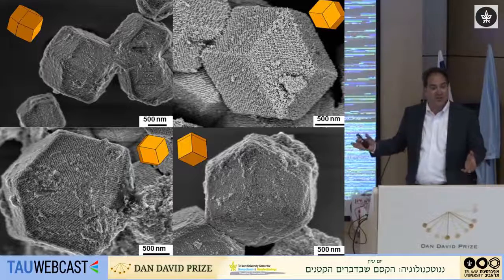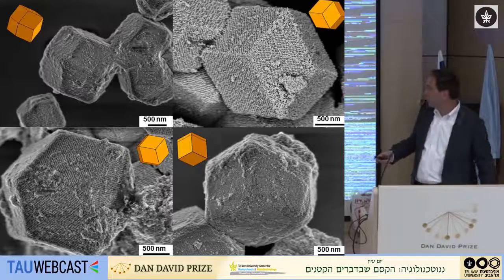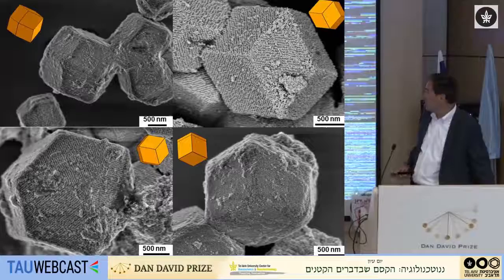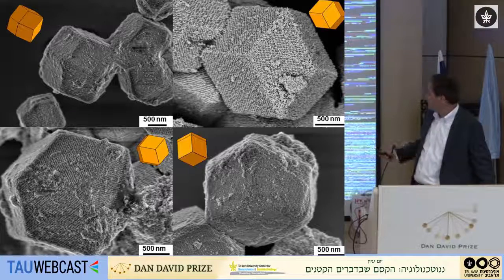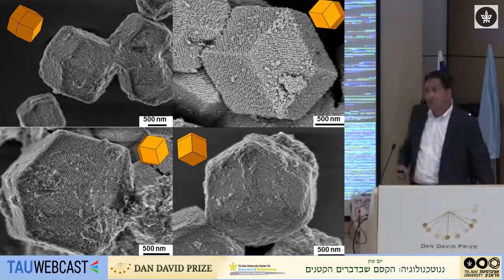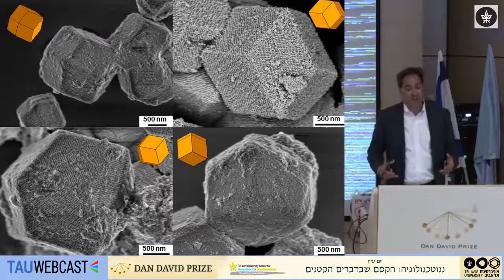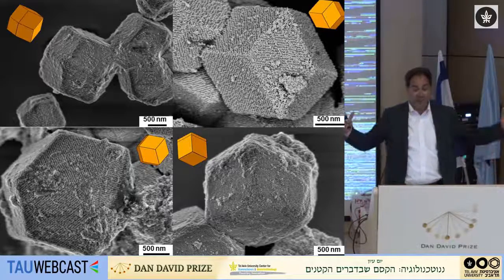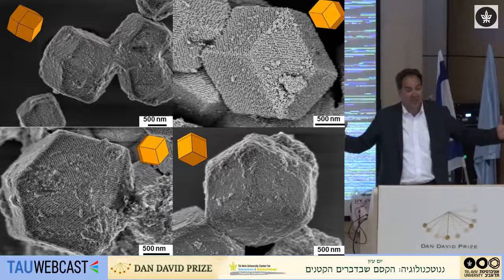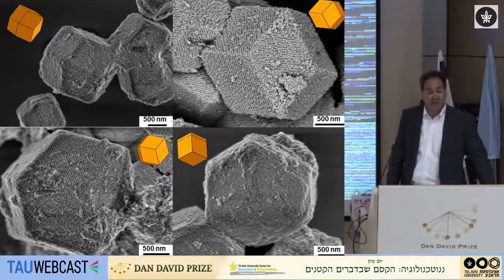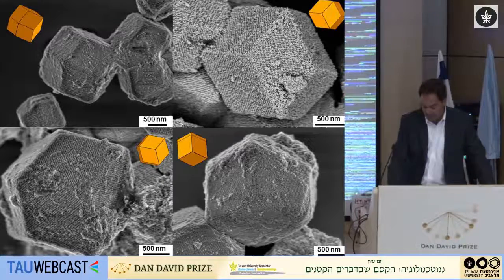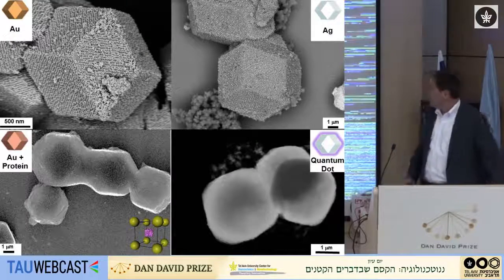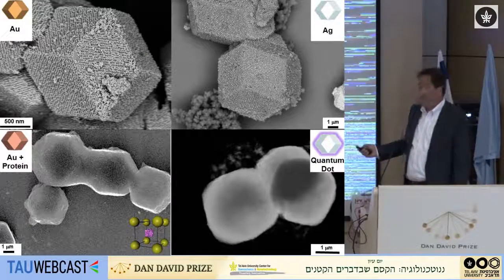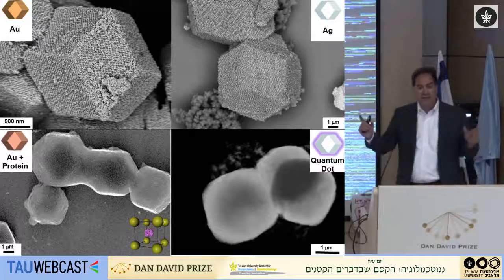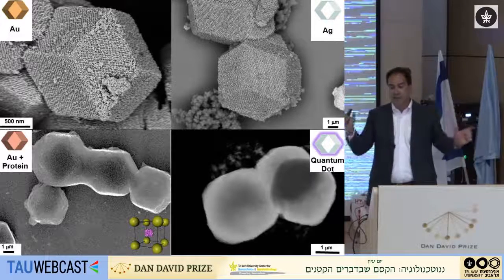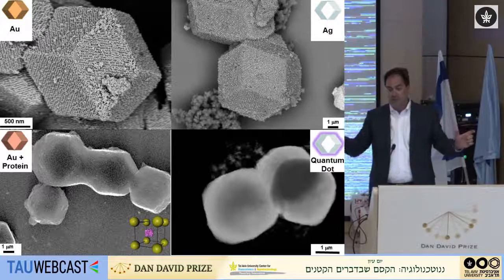It's limited to your understanding of how you make these structures and whether you can get to, as I said, the thermodynamic sink. And you can see very clearly here, beautiful facets. This is going to be a fantastic way of studying crystallization. These are atoms on steroids, big structures, easier to visualize. It allows us to use a lot of techniques that we can't use with atomic-based systems very easily. But it extends to, as I said, anything. The particles go along for the ride. This is that important concept of bond-independent control over atom-independent control.